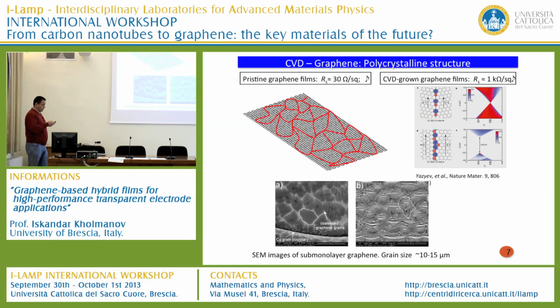Pristine graphene with no defects on a silicon oxide surface may have a sheet resistance as low as about 30 ohm per square. But if you fabricate transparent conductive films from CVD grown graphene, the sheet resistance is about 1 kilo ohm per square, much higher than pristine graphene. The reason for such high sheet resistance is the different types of defects present in the CVD grown graphene.